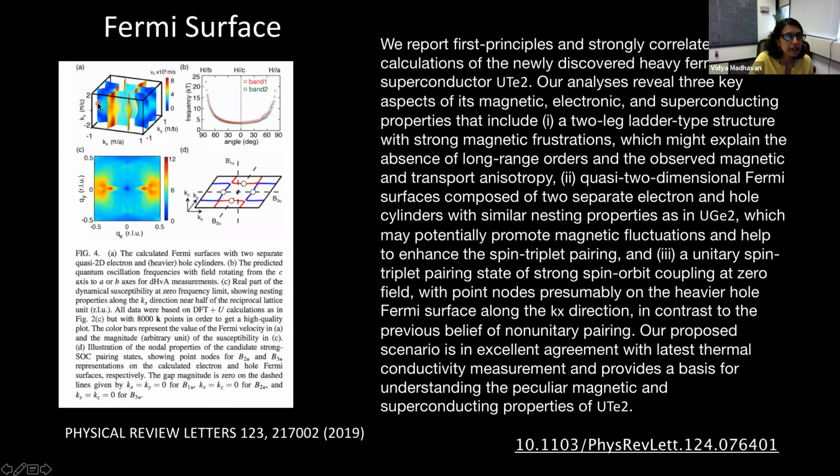So this is the Fermi surface. Here are some of the bands right near the Fermi energy. I would say that this is still the beginning stages, and we don't have a full grasp of the band structure yet. There are heavy bands near the Fermi energy. There's more than one band near the Fermi energy, but that's all I can tell you. And this is approximately what the Fermi surface looks like, and ARPES data shows something that looks like this. Now, how much of these bands are tellurium bands, how much of this band is a D band, and how much of it is F? There are 3 bands in this material: P, D, and F. And how much of this Fermi surface comes from those 3 orbitals, I cannot tell you. All right. Thank you. Sure.